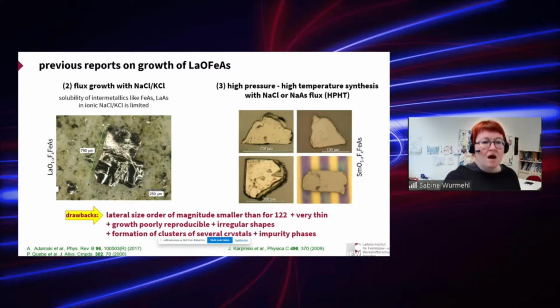There have been reports from the Kapinski group, Nikolai Zigadlo, using high pressure, high temperature synthesis, shown here on the right-hand side. But here you have very irregular shapes. Also, the growth is rather irreproducible, and you also have formation of clusters of several crystals and also impurity phases. So you can get crystals with these methods, but their quality and size is not at all comparable to the crystals of the other pnictide superconductors.